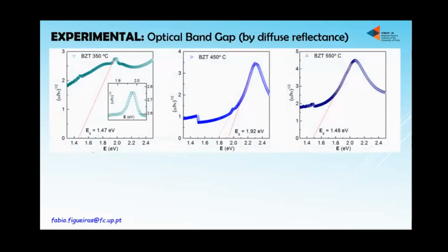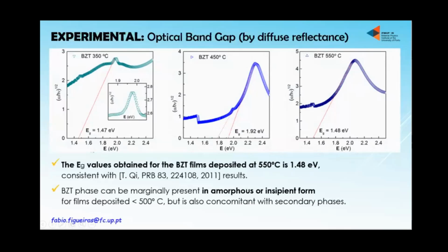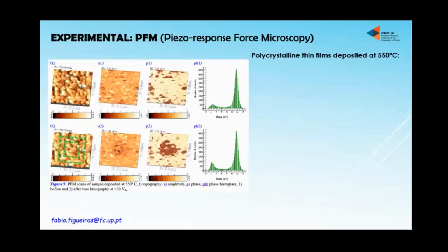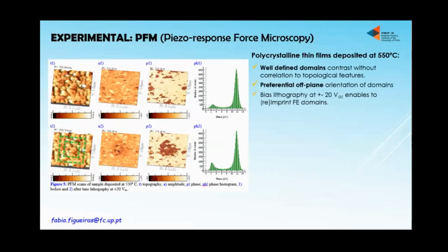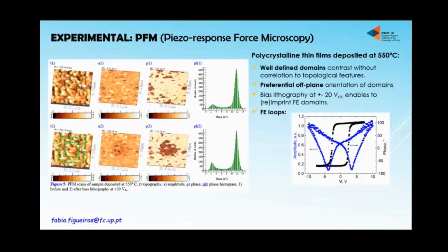So let's check this, and we found that the material has a band gap exactly in the range that was predicted by the DFT studies, and the other materials with different phases, either the amorphous or the secondary phase, completely fail the band gap. So this is also encouraging. We got the right crystalline structure, we got the right band gap. So we go now for piezo force microscopy. We got imprints, and especially we have the hysteresis loops that are demonstrative that the material has ferroelectric properties.